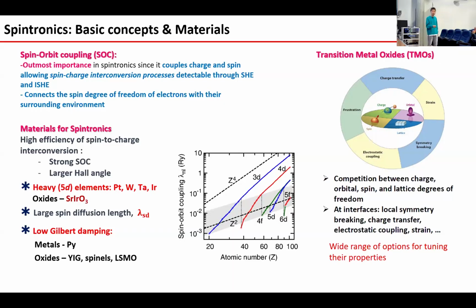Then another important factor is to achieve a larger spin diffusion length. So it's quite important to utilize low Gilbert damping materials. In the metallic materials, we typically utilize permalloy, and oxides, for example, YIG, bismuth-doped YIG, and LSMO. Why is it very interesting for us to utilize transition metal oxides?